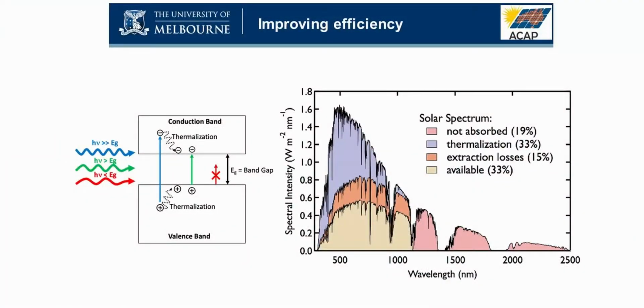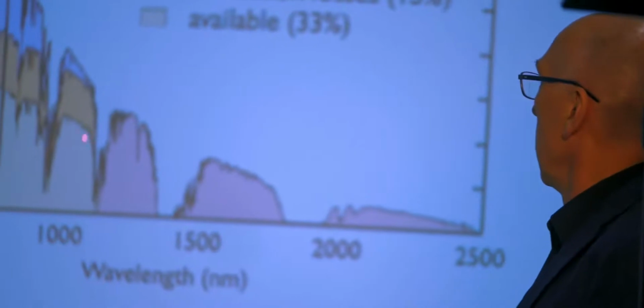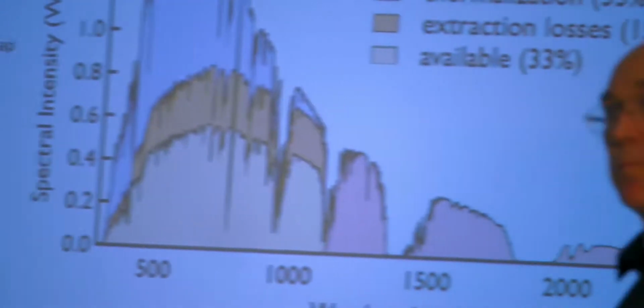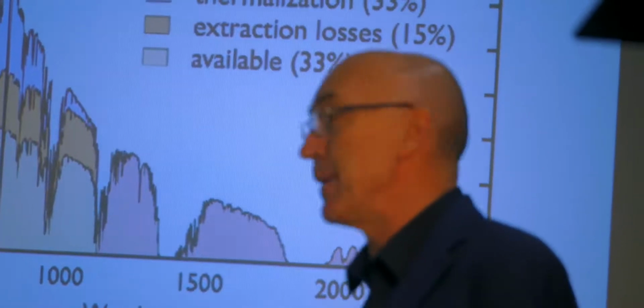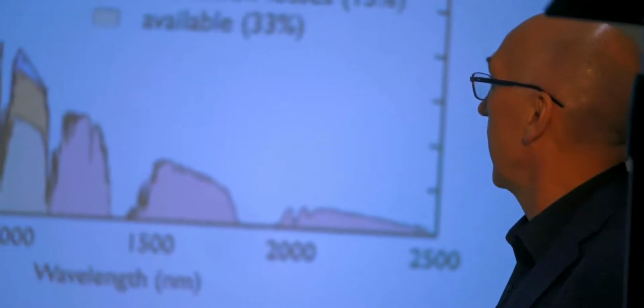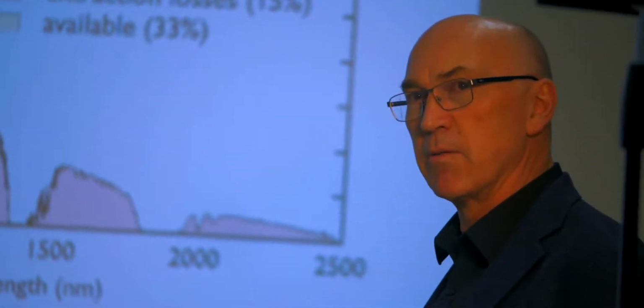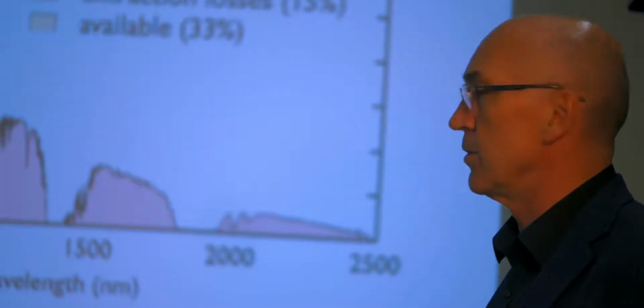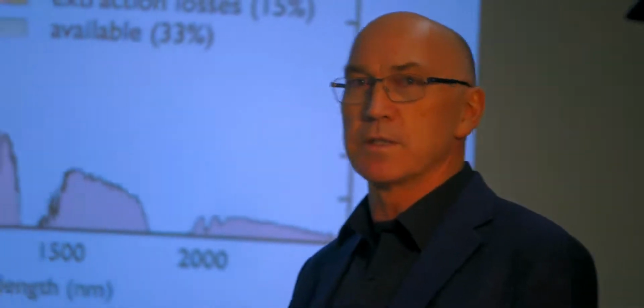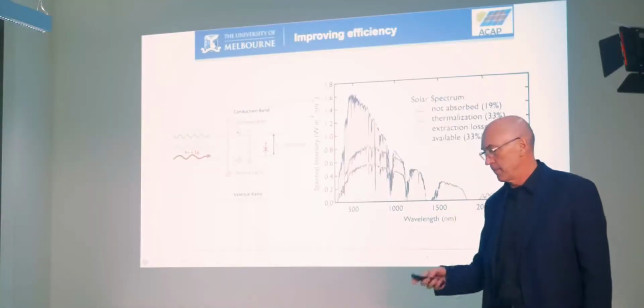And so we can look at that in this image that I took off the web. And so we can summarize that. So basically, and this is the band gap for silicon, anything below the band gap is not absorbed. So those photons we can't use. Anything above the band gap, we will absorb. We will generate one electron hole pair per photon at best. But that means that all that extra energy is lost. And so that's that grey bit here, the thermalization. So we should be able to try to use this. And of course, no system is perfect, so we have extraction losses, which we can't do anything about.